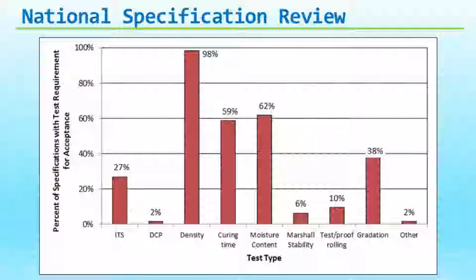We see acceptance tests based on ITS. That's a problem because it takes a long time to do an ITS test. It's got to go through a curing phase, and then you do wet and dry tests on it. So that can take anywhere up to 5 to 6 days. The project's usually finished before you get the test result.